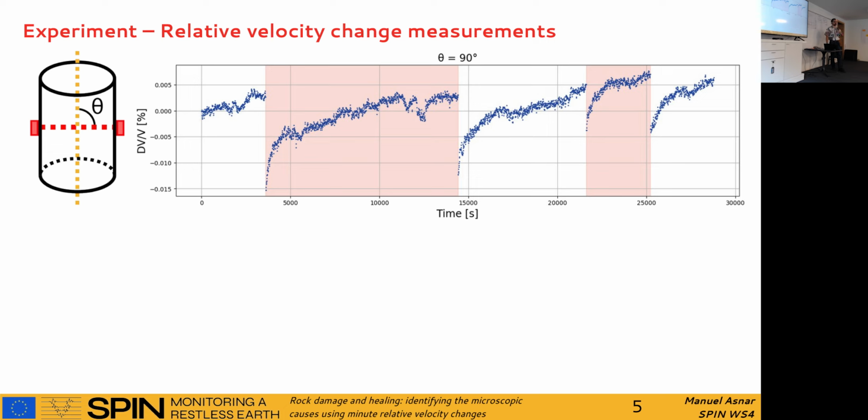So this might come as a surprise compared to what Eric was telling us yesterday, which is naturally you compress a rock, you would expect the stiffness or the rigidity to increase, which is not what seems to be happening here. But then, even more interestingly, you remove the uniaxial compression, and the exact same thing happens again. We get softening, which then recovers to its original level. Just for reference, again, the amount of time that it takes. And then we compress again, we decompress again, and the same thing happens twice. So this is what we see for a horizontal wave.